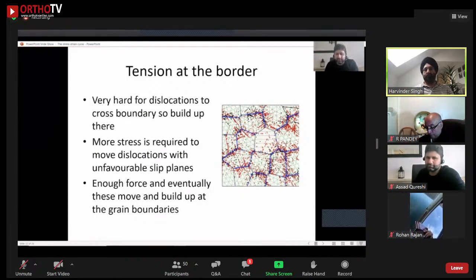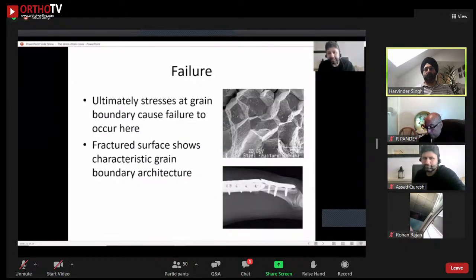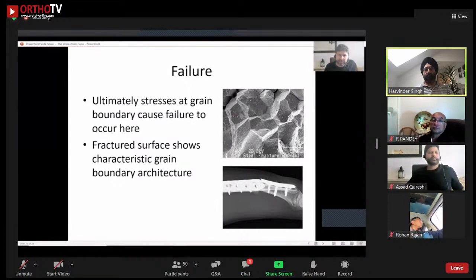With enough force, eventually all the dislocations have moved and there's nowhere to go. And that's when failure happens, because the stress built up at the grain boundary is too great and you essentially have a microfracture. All these microfractures across the grain boundaries coalesce and cause failure. And that's why failure is quite spectacular and sudden. And when we look at the fractured surface of the metal, it undulates. And what we see on a microscopic level are all those grain boundaries.